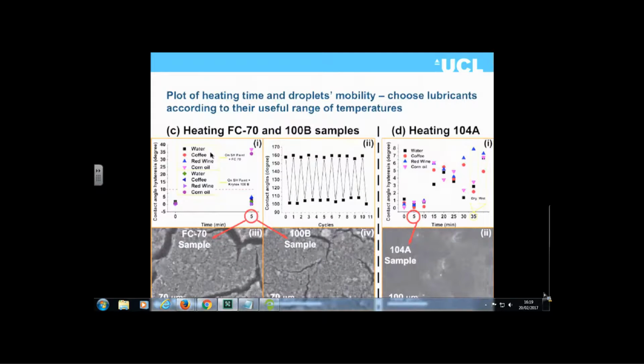This shows water, coffee, red wine and corn oil, which we've looked at, and the contact angles for hysteresis associated with these materials. It also shows the particular cycles which we've done through the contact angle cycles as we've run through the material.